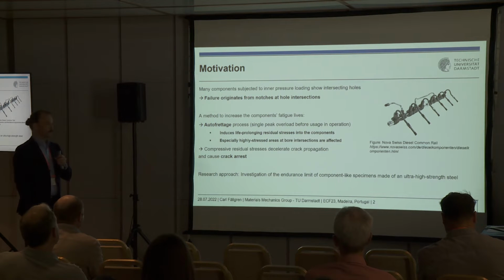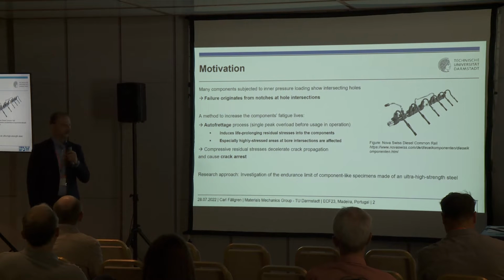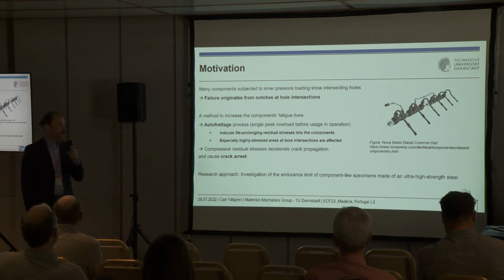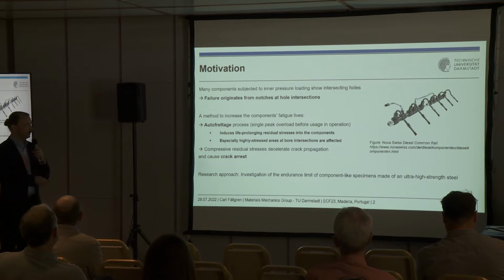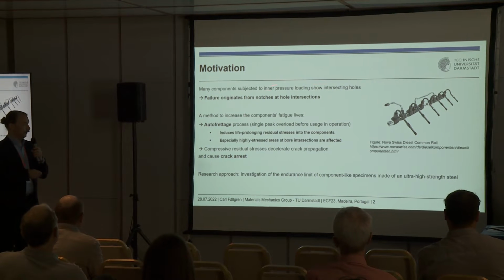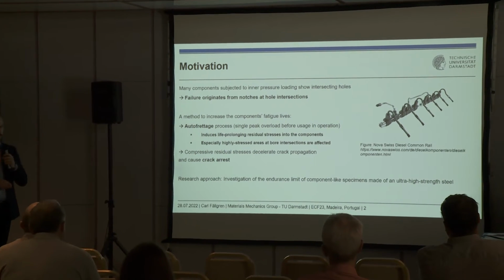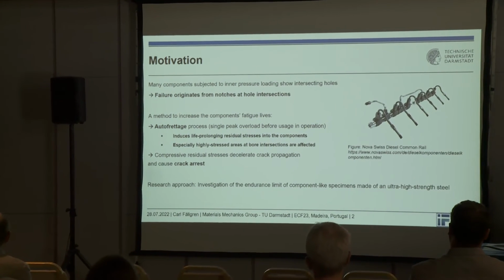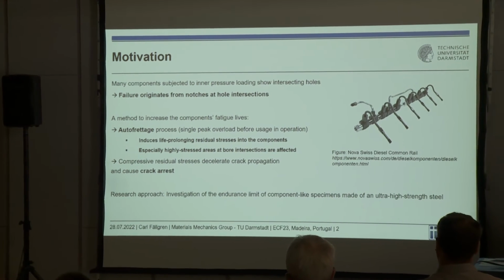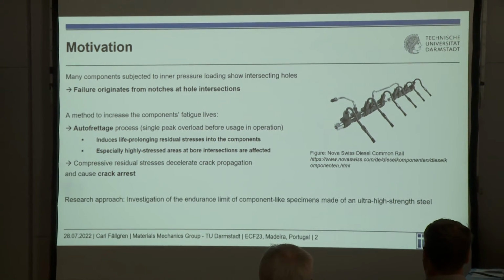So the motivation is that many components are subjected to inner pressure loading, like the common rail shown here on the right side, which is a common rail for highly compressed diesel injection systems. They show intersecting holes, as you can see here. You have one main bore and all those crossing holes. And failure always originates from the notches at the hole intersections.